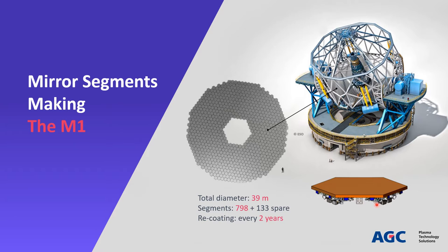The weather conditions in the desert are aggressive for the coated mirror surface, due to pollution, humidity, potentially causing corrosion and sand storms, and so the reflection will gradually reduce in time. ESO will install two magnetron coating machines in their Paranal Observatory, which is about 25 km from the ELT, in 2021. They will be used for the initial coating of the mirrors and for the re-coating of the mirrors after stripping. ESO intends to coat two segments every day and needs a reliable coater based on an industrial design. It is estimated that the re-coating of the mirrors will be necessary with a two-year interval.